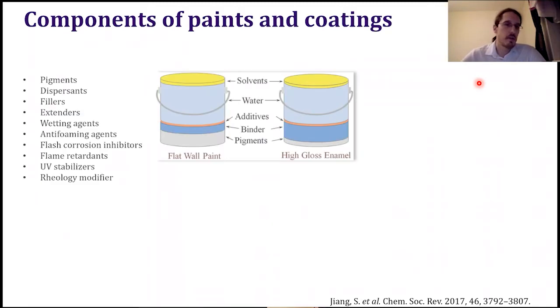So as you can see, for paints and coatings, there's quite a lot of water in there, and just a little bit of solvent because the regulations are getting more and more strict. But then we have quite a lot of additives, which are mainly rheology modifiers that make the paint thicker, for example. And we have wetting agents which let the paint spread much better. And we have many other additives which can be added in small amounts. Then we have the pigments, which, as the name says, give the color to the coating.